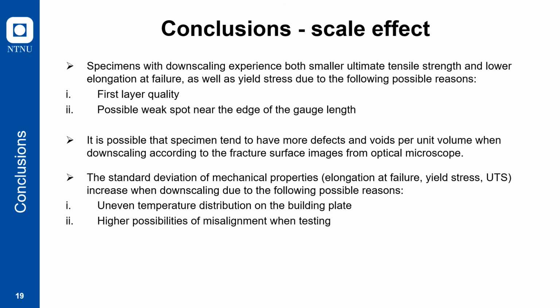And the second is the possible weak spot near the edge of the gauge length, as demonstrated before. Another reason is that it is possible the specimen tends to have more defects and voids per volume when downscaling, according to the fracture surface images from the microscope. And also, the standard deviation of the mechanical properties like elongation at failure, yield strength, and UTS increases when downscaling, due to two reasons. First, the uneven temperature distribution on the building plate when fabricating. And second, because the specimen gets smaller, there's a higher chance of misalignment when testing.